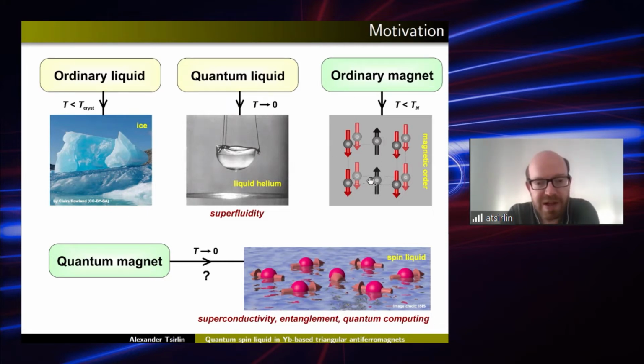But then if we put some additional quantum effects into the magnets, then perhaps we can suppress this magnetic ordering transition and reach the situation when down to zero temperature, the magnet remains disordered but strongly correlated. And that's basically what we call, at least on the most basic level, spin liquid. So the collection of spins which do not show long-range order, which don't show any symmetry breaking, but which fluctuate, but which at the same time remain strongly correlated. There is some sort of short-range order, but no long-range order.